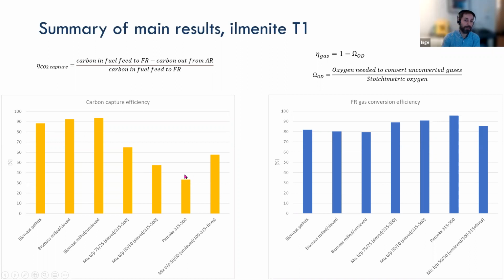And then we see a really drastic drop in the CO2 capture efficiency, which is because quite a lot of the fuel is not gasified in the fuel reactor and is transferred to the air reactor, where it combusts and leaves the air reactor as CO2.